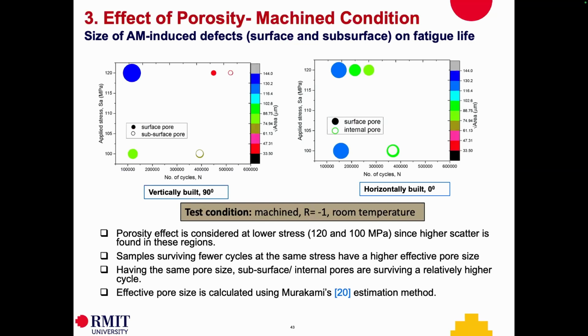Let's summarize what we found, what lesson we learned in this diagram. We considered the porosity effect at low stress level because higher scatter is found in this region. That was our problem. We couldn't relate with porosity very well. And what we find here, look at this diagram, vertically built and horizontally built. For the same stress amplitude, if the pore size is smaller, you get a higher fatigue life. Very good news. Same stress amplitude, pore size is smaller, as dotted by the circle, you get a higher fatigue life.